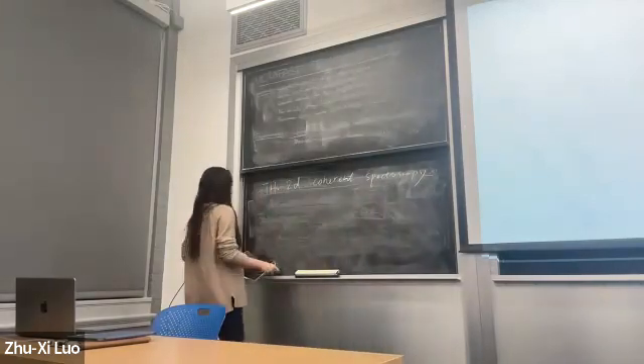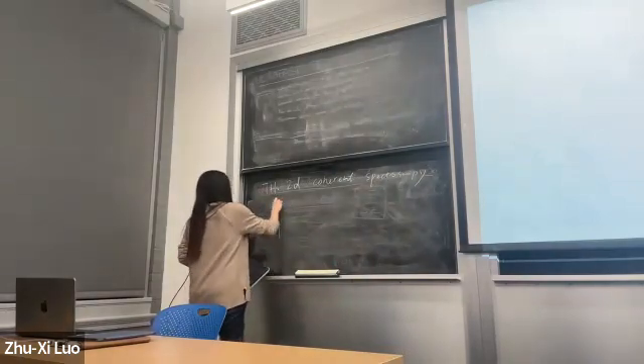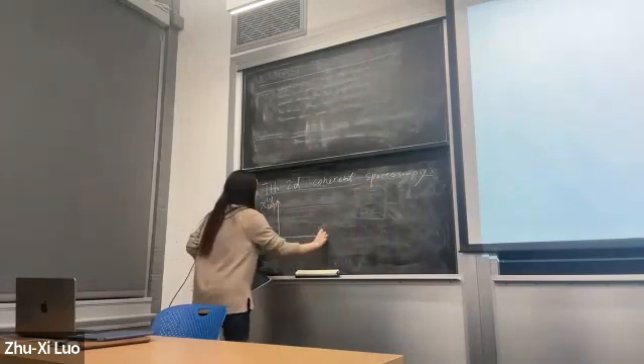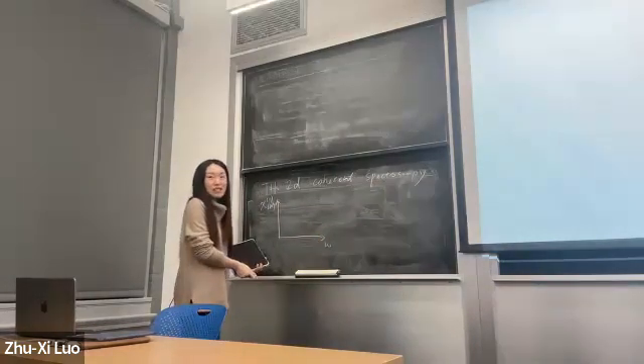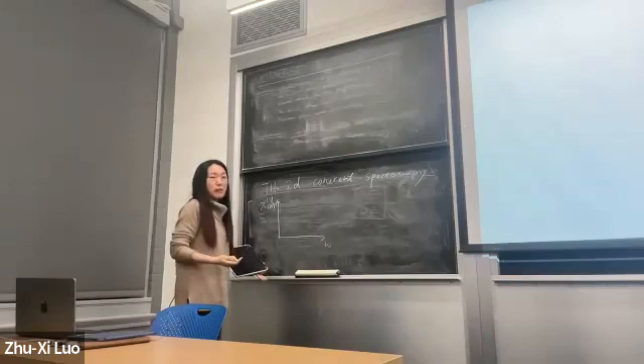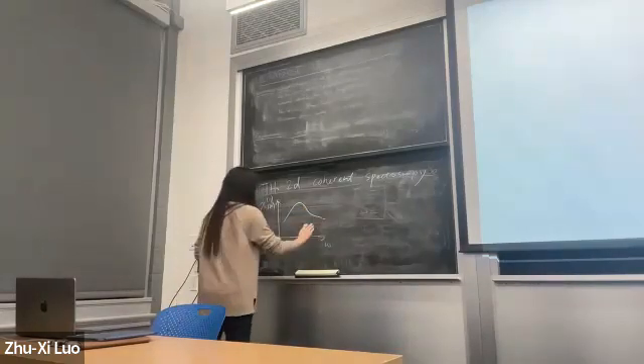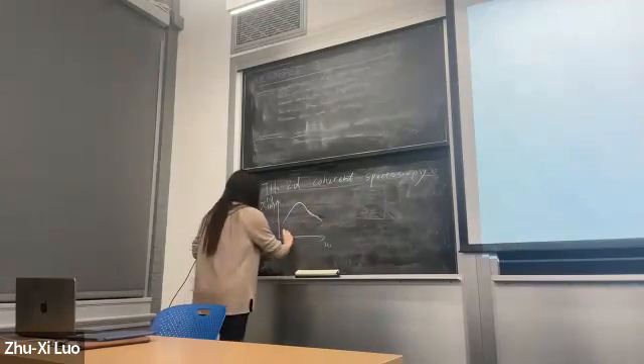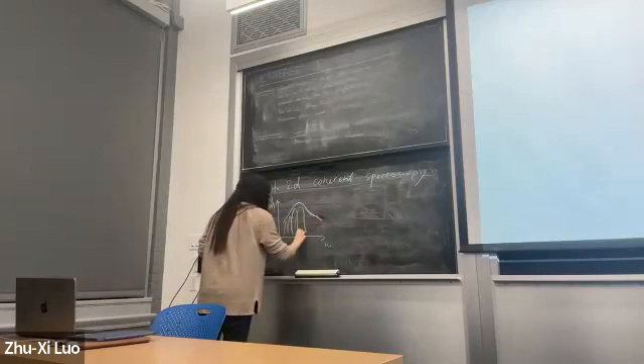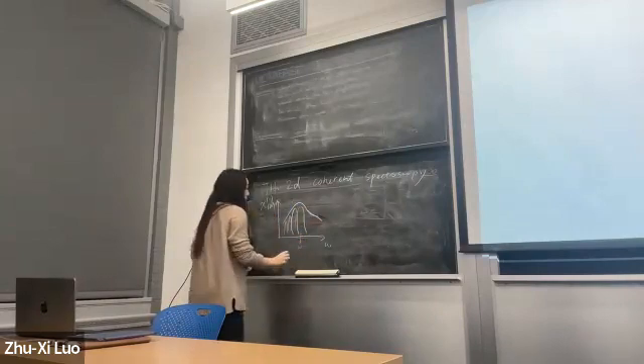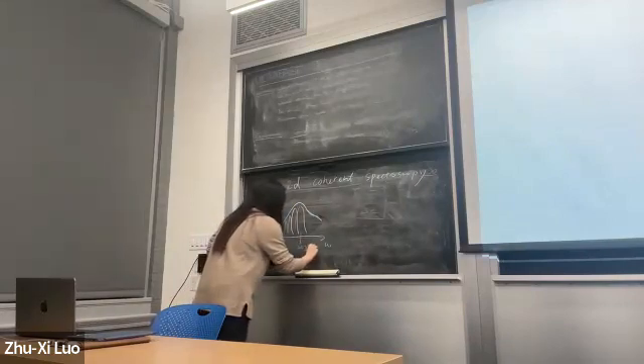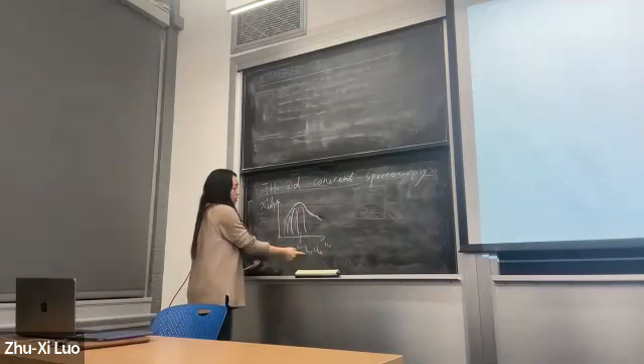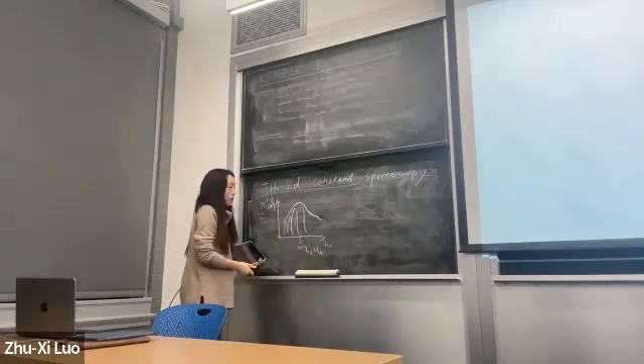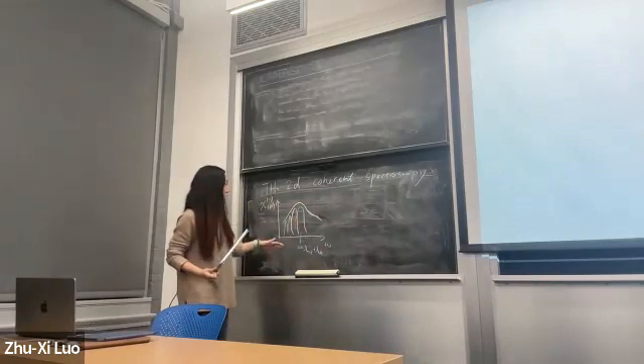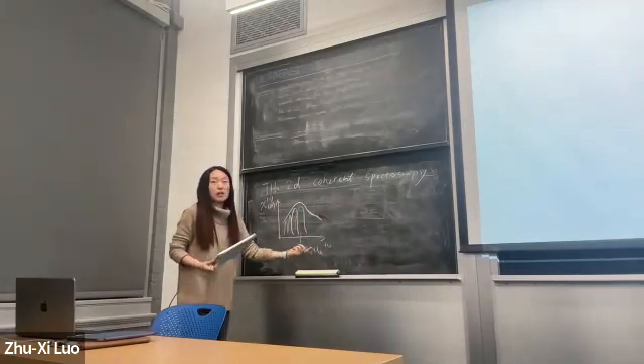Okay. Linear spectroscopy, chi1 of omega. When you have fractionalized excitations, for example, you create spinons in pairs. You typically get some broad spectrum. Each pair of spinons, so this is basically a convolution of various things, right? Each sharp peak is centered at frequency omega, the summation of lambda minus k plus lambda k. Lambda k is the dispersion of the single spinon at momentum k. So this broad continuum is basically describing how the energy and momentum can be shared between the pair of spinons.